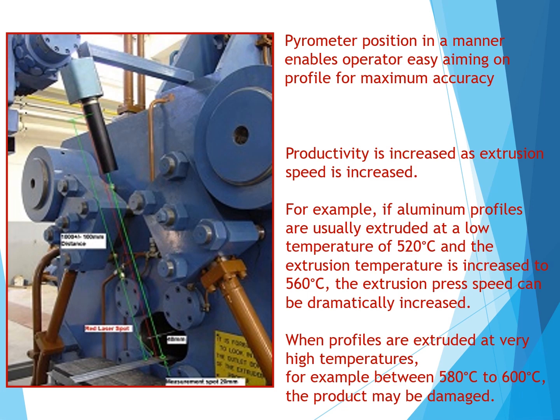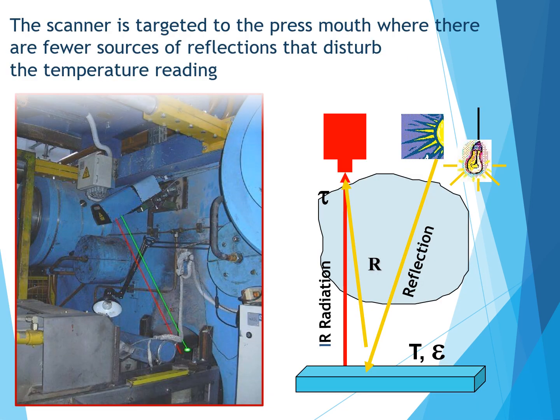Productivity is increased as extrusion speed is increased. For example, if aluminum profiles are usually extruded at a low temperature of 520 degrees and the extrusion temperature is increased to 560 degrees, the extrusion press speed can be dramatically increased. When profiles are extruded at very high temperatures, for example between 580 degrees and 600 degrees, the product may be damaged.